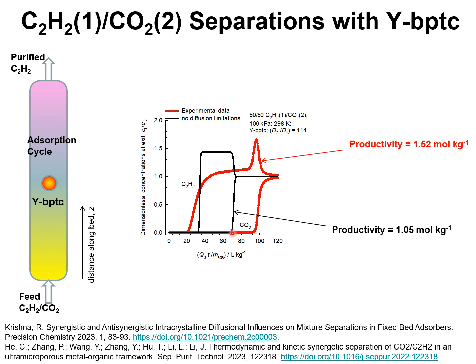I compare here the breakthrough experiments with breakthrough simulations in which diffusional influences are completely ignored. The breakthrough simulations are described in my paper in Precision Chemistry 2023, and if we compare the breakthroughs, we note that the experiments show that C2H2 breaks through earlier and CO2 breaks through later than anticipated in the simulations in which diffusional influences are neglected.